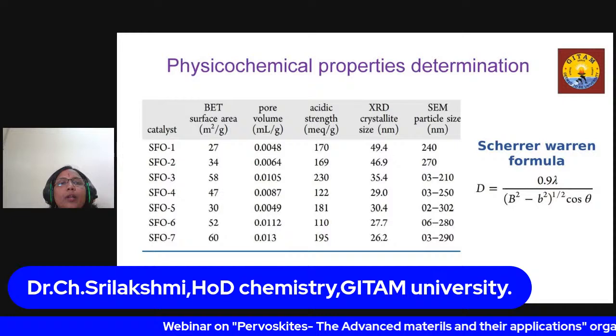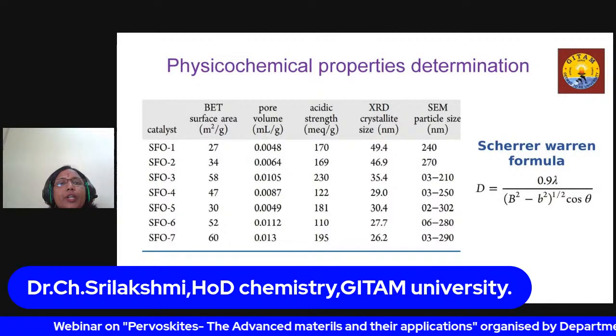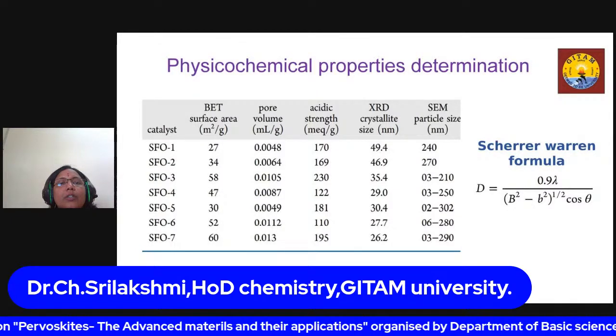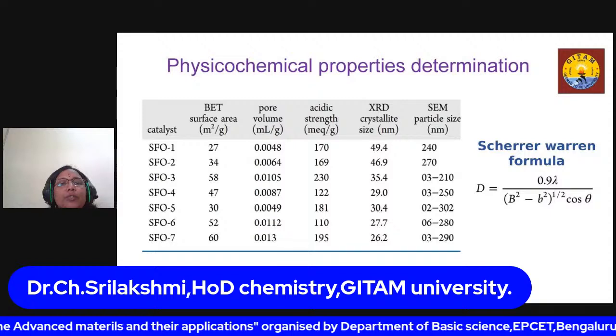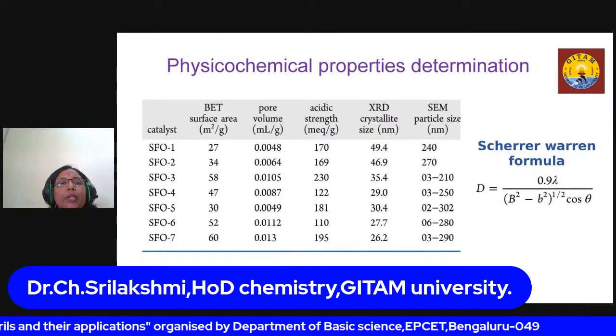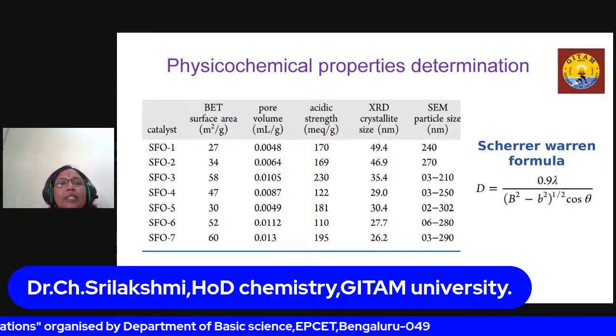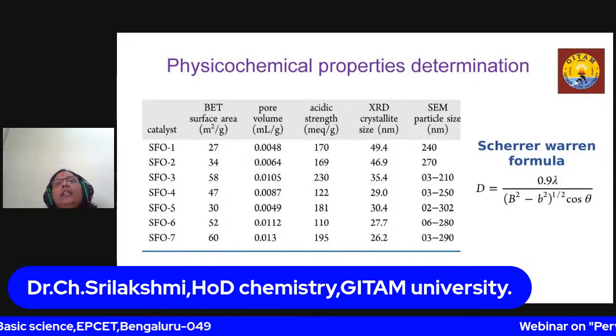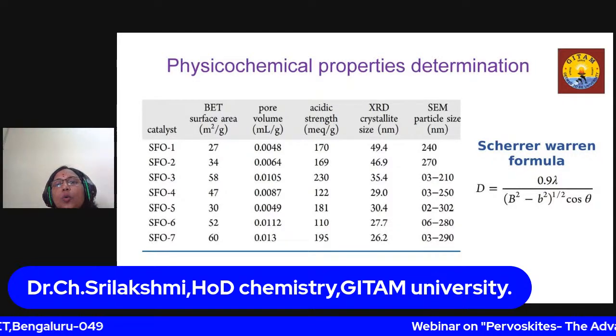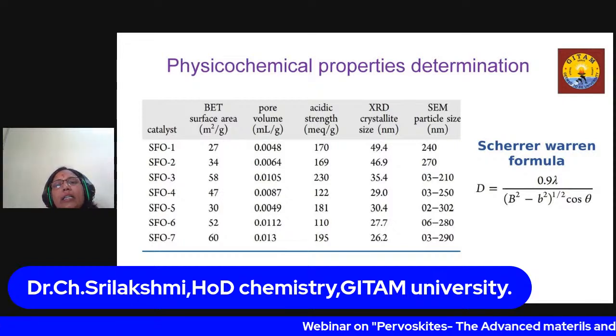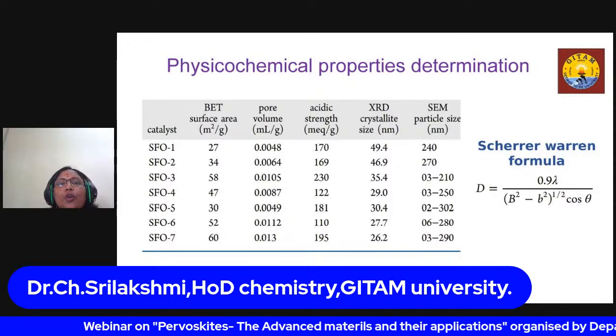And for physiochemical properties determination, again you can see the first three samples were prepared using individual fuels, and 4 to 6 are combinations of fuels. You can see surface area improved, pore volume improved. When you come to acid strength, it goes down. So the acid strength of this material goes down when we use the combination of the fuels.